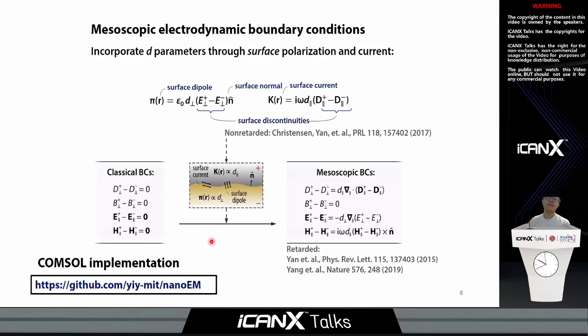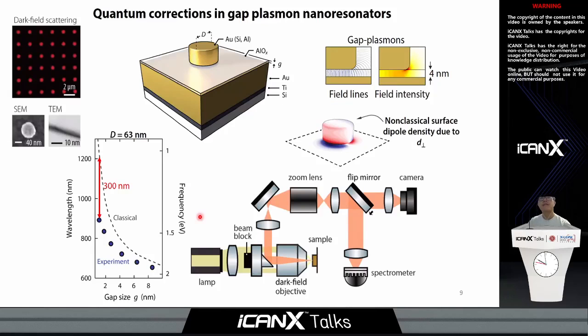To experimentally test this framework, we chose a quintessential gap plasmon nanoresonator comprised of a gold nanodisc and a gold substrate. In between them, there's an aluminum oxide thin layer defined by atomic layer deposition. It is known that these structures support well-confined gap plasmons underneath the nanoresonators. And our non-classical calculation shows that the non-classical dipole density is also pronounced underneath the nanodiscs. So this calculation indicates that we may be able to observe pronounced non-classical effects in this setup. And indeed, that's what we see.